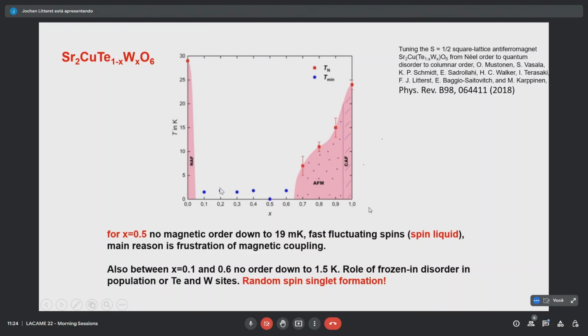That this is not going down to zero is the only reason we didn't get beam time for this low temperature equipment. So our lowest temperature was only 1.5 Kelvin. It was only a suspicion that it stays down like it does for the 0.5. In the border regions, we still find order extending down to even 0.6. On the other side, it's very narrow. It's very close to the tellurium compound, so that with mixing in tungsten we already lose magnetic order.